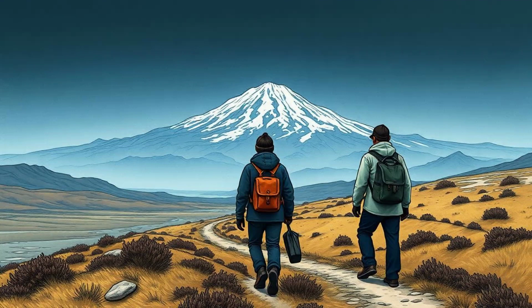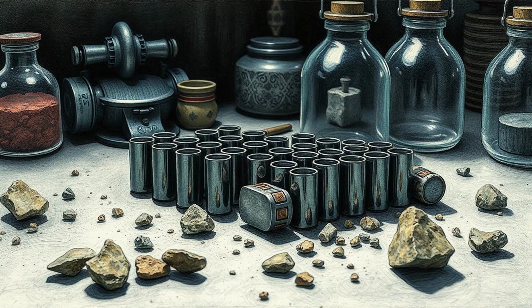The story first gained attention in 2002 after a team of scientists went to investigate. Samples of the pipes were taken to be analyzed. The analysis, done by the state-run Xinhua agency, found that the pipes were mostly iron oxide with a high amount of silicon dioxide and calcium oxide. Interestingly, they also found that 8% of the material in the pipes could not be identified.